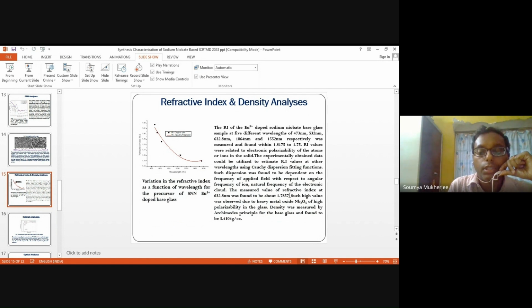This high value is coming due to the presence of niobium oxide, and niobium, being a heavy metal oxide, gives polarizability, which raises the refractive index value. Density was calculated using the Archimedes principle, and it is noted to be around 3.41.